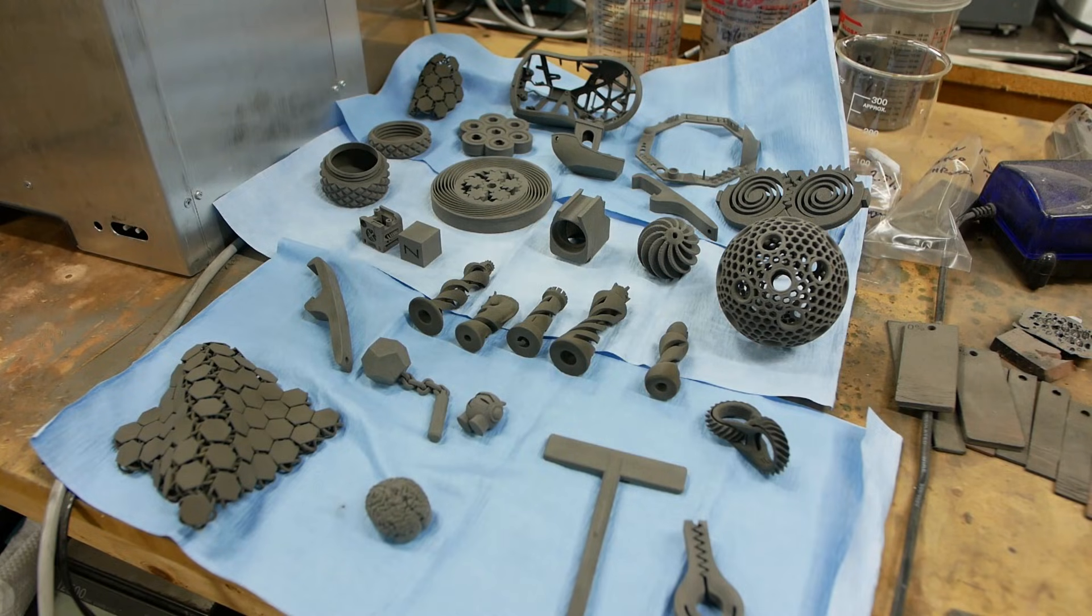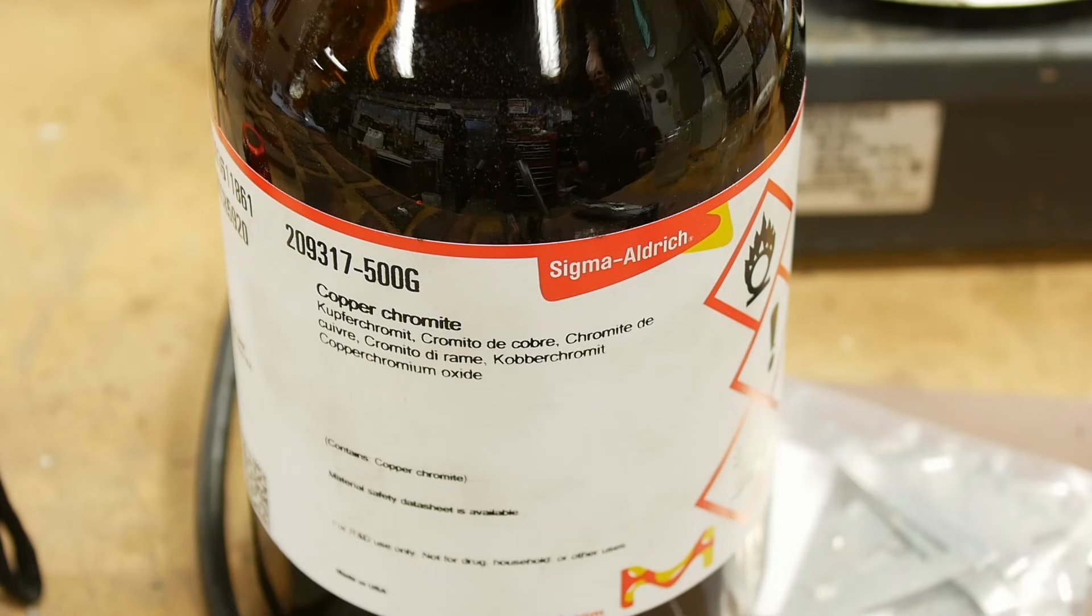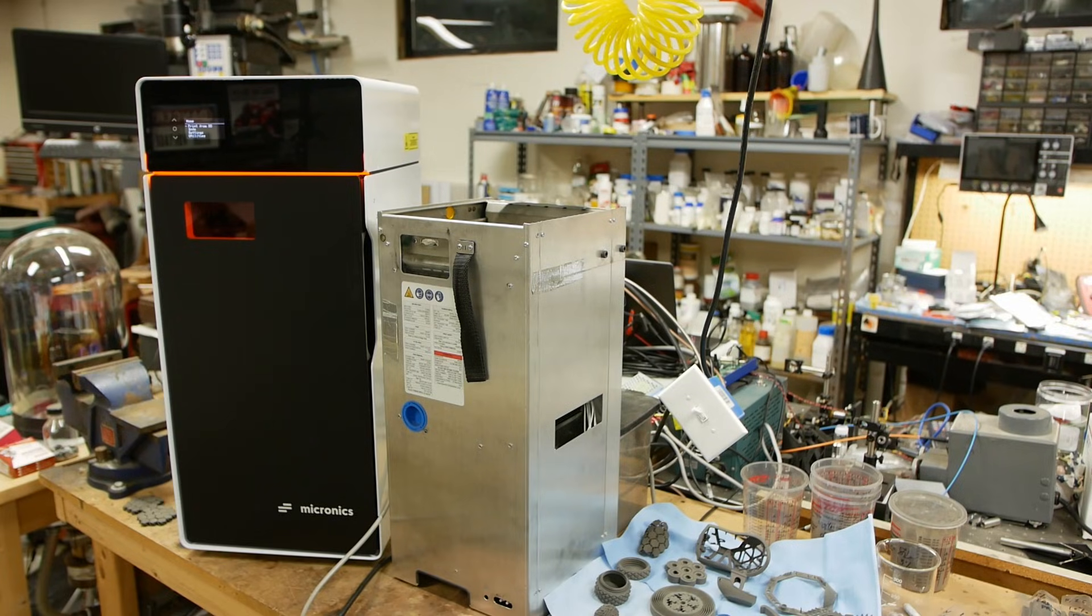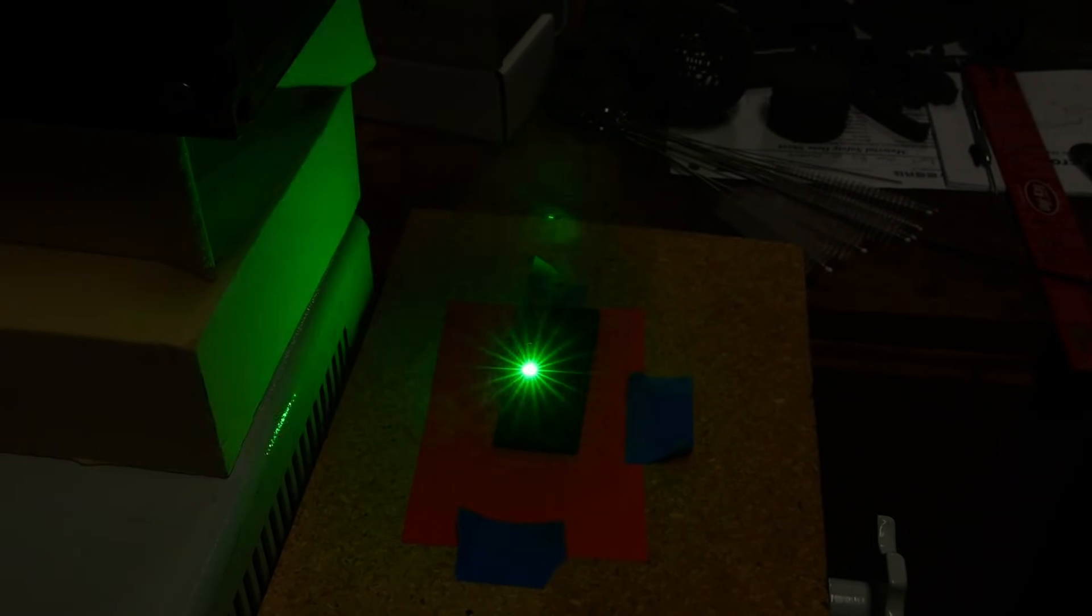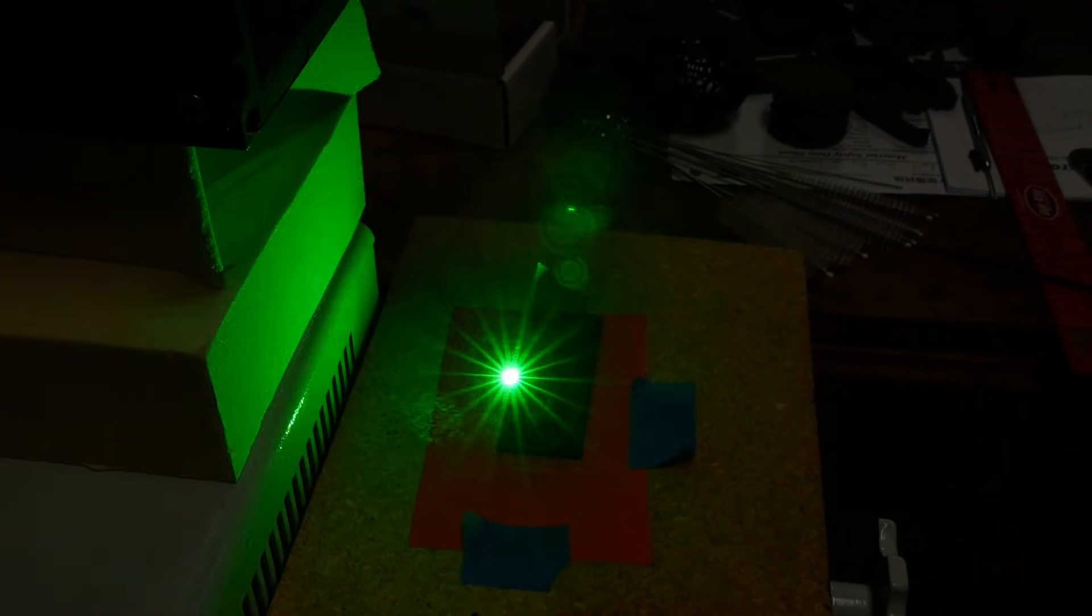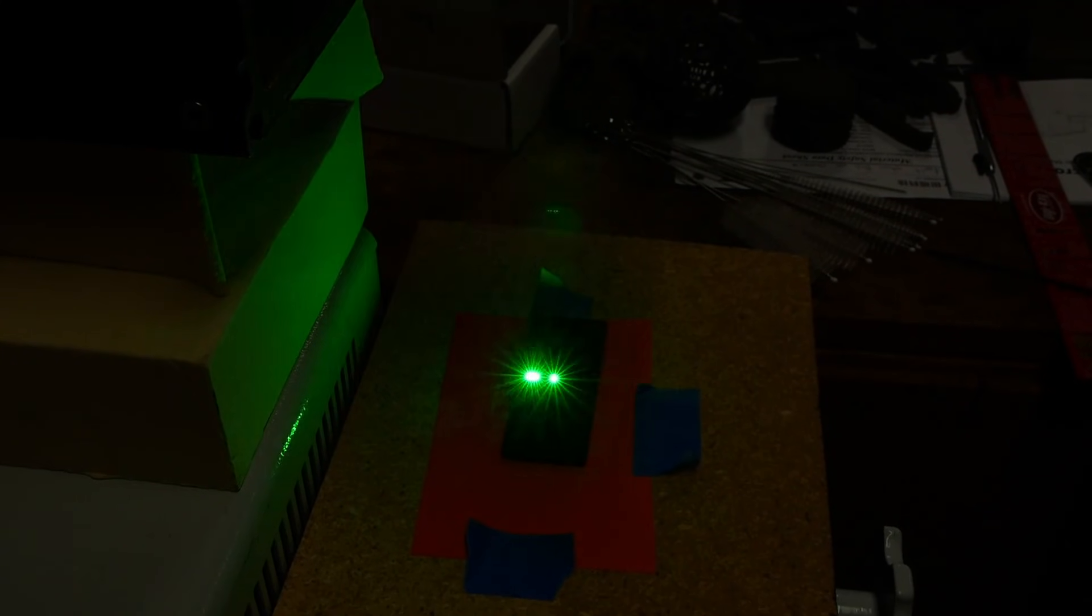Luckily, the catalyst that we're using is quite black. It's copper chromite, which is a copper chromium crystal, it's an oxide, and it is not conductive and it also is not a catalyst until it gets hit by a pulsed laser. You can shine the continuous wave laser on it all day long and nothing happens. It still won't plate any copper. It has to be hit by a pulsed laser, which has pulse powers of tens or hundreds of kilowatts. And so it's kind of a fundamentally different process than the laser that's in an SLS printer.